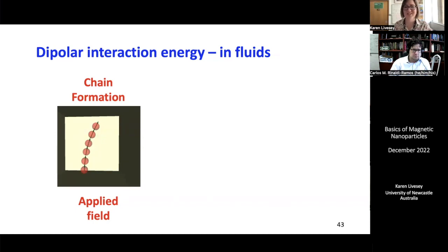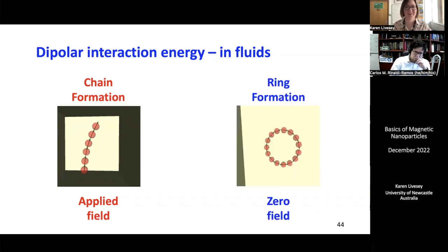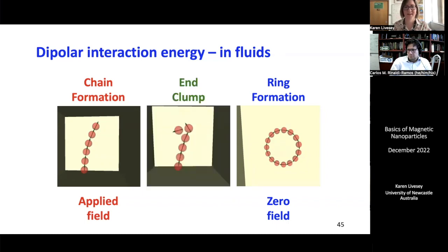If the thermal energy is too big, the chain will blow apart because we have that competition again between disorder and order. In zero field, we can see little rings form. Again, this will completely reduce the stray field energy, so that can happen. And then in between, say a weak field, we see all sorts of different configurations happen. So this is just one example. A student of mine called it an end clump.